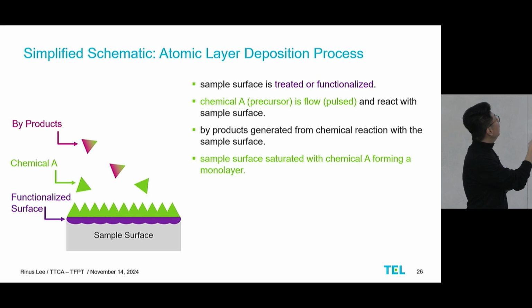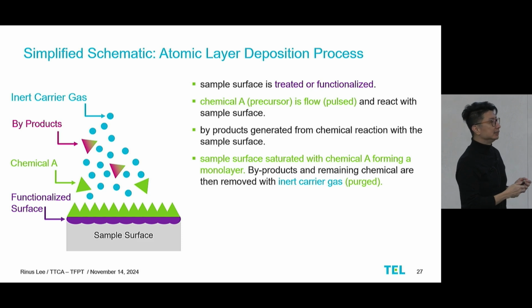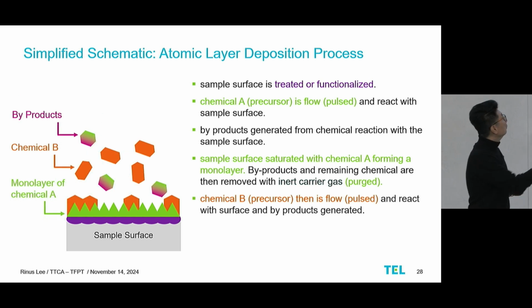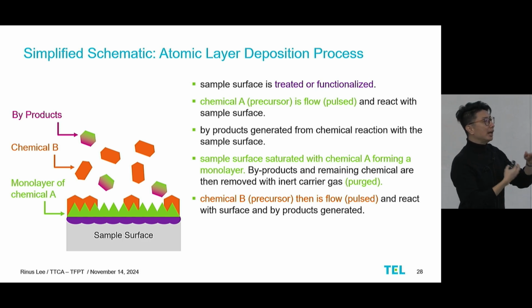But what do we do with the remaining chemical A and byproducts within the chamber? At this stage, we flow an inert gas, typically like argon or nitrogen, in these blue circles. We flow it in, and then we pump it out of the chamber, removing any remaining chemical A or byproducts itself. What we do next is we introduce another chemical B, and it flows into the chamber again and reacts with the surface. The surface this time will be chemical A. By reacting chemical A and chemical B together, we could form different sorts of films that we want. It could be an aluminum oxide or a titanium nitride, depending on the chemicals that you choose.